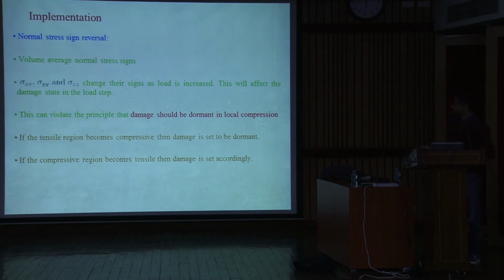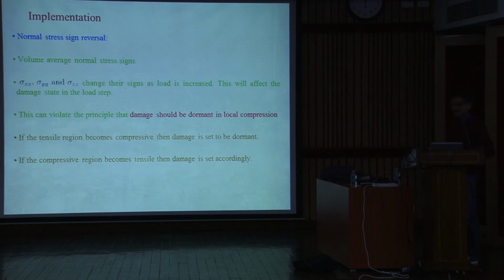At each step, you have to take care that we do not want the damage to increase during compression. As we said, it should remain dormant in local compression. It should grow only when the region becomes tensile; otherwise it should remain dormant. So if that region is tensile, then you have to go back and look at the damage indicator and the corresponding thermodynamic forces, and if your damage indicator is more than the previous one, only then are you updating your damage indicator. Otherwise you go with whatever is there in the previous step. Because of this frequent reversal of local tension and compression, you have to ensure that these damage indicators or these regions are the same in your load increment.